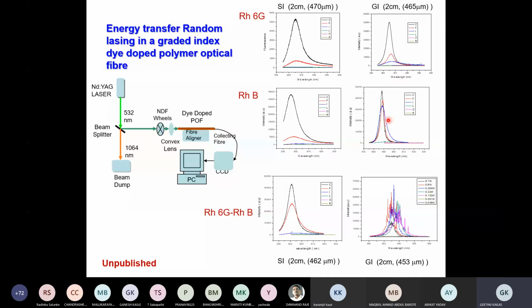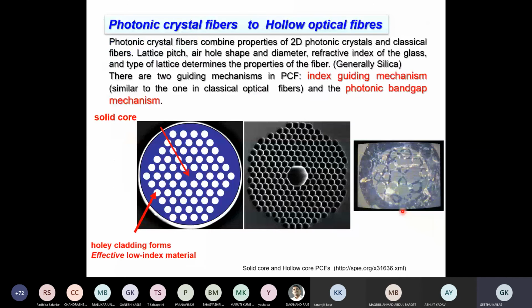So graded index structures are confining light more efficiently, and they can give you amplified spontaneous emission easily compared with the step index, and also they generate lasing frequencies beyond a certain pump power. So no lasing was observed in any of the step index structures, but lasing was observed in the graded index structure. So then later there was a considerable interest in the photonic crystal fibers.